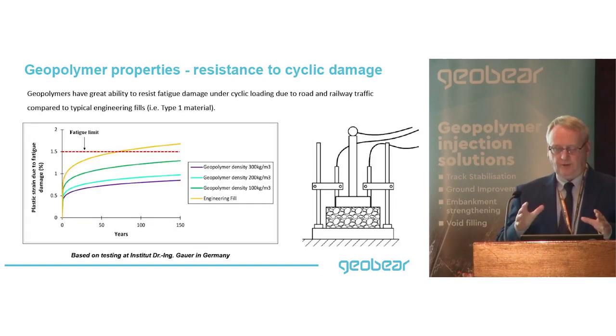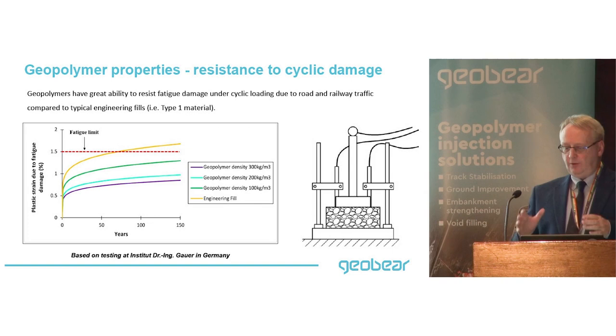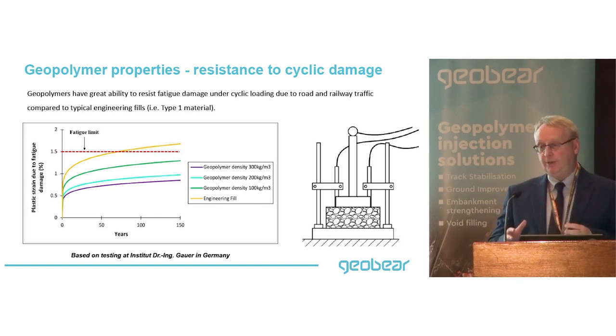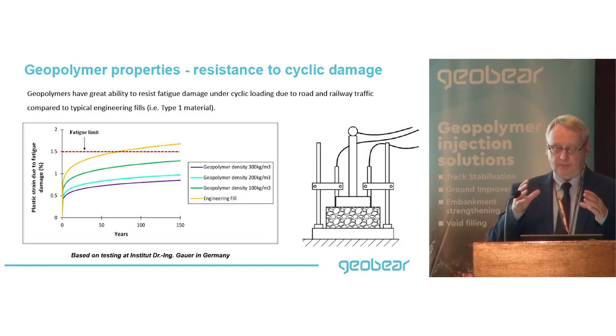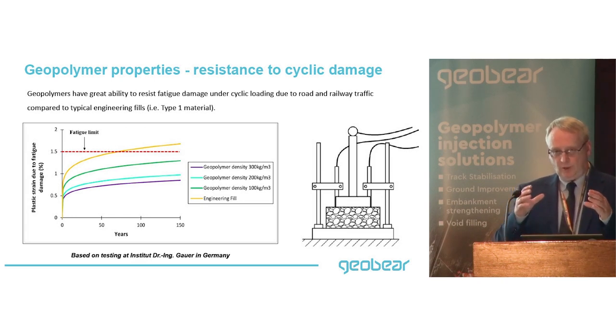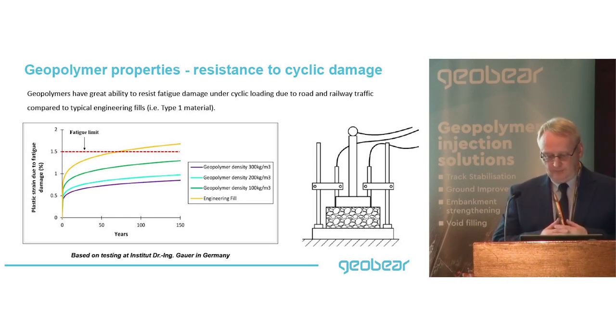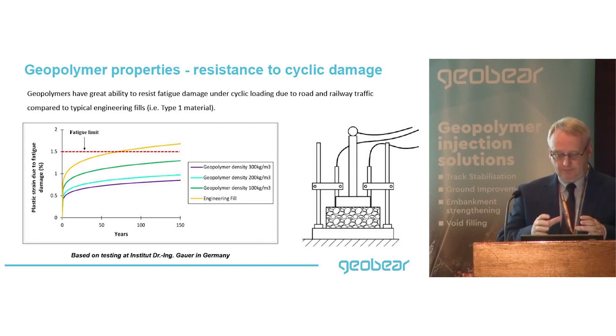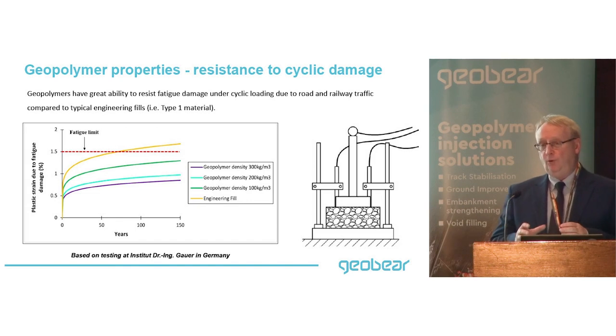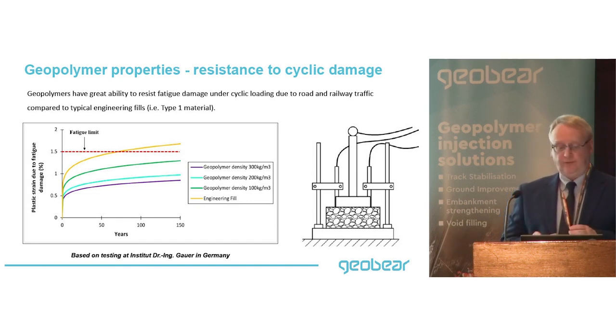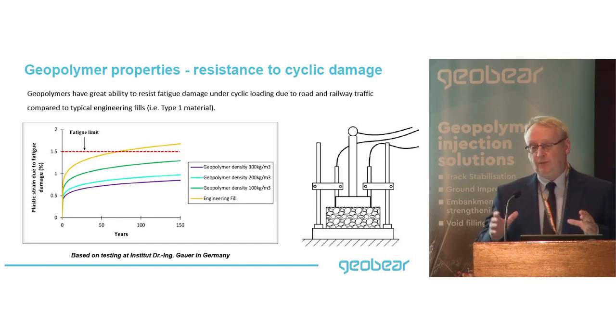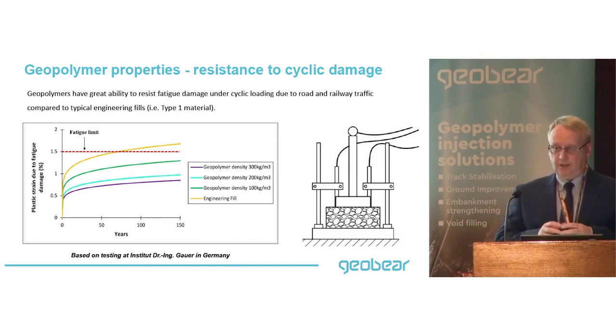Another thing with geopolymers is their ability to resist cyclical damage. The polymers have been tested to see what settlement you get under cyclical loading. And what we've found is that the performance of geopolymers at different densities will generally outperform normal, typical engineered fill, type 1 compacted fill. If you inject geopolymer into those materials, you'll find that their resistance to cyclical damage is greatly increased.